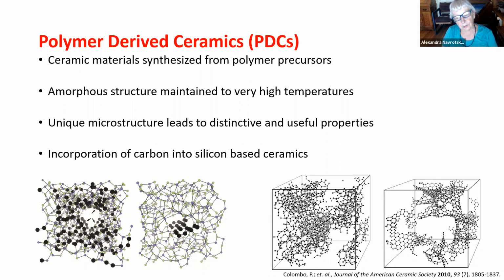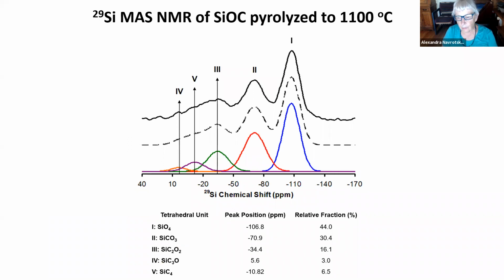But what we've really focused on then is the synthesis, structure, and thermodynamics of the polymer-derived ceramics. Here we show that indeed one can quantitatively count up the number of these different bonding groups, SiO4 groups, SiO3C, SiO2C2, and so on and so forth. And the silicon magic angle spinning NMR gives a tremendous amount of useful information. This is just a spectrum of one of the polymers that was pyrolyzed to 1100 degrees C, which made the essential high temperature ceramic material.